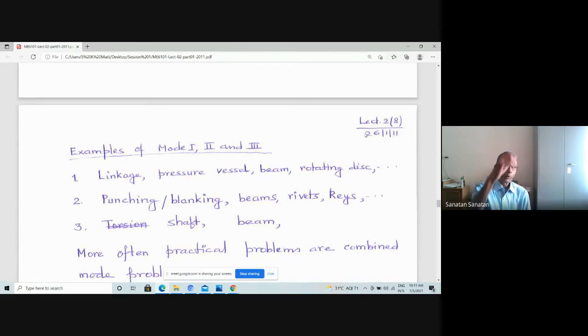Then in the case of a shaft, if you just think of a keyhole, or rather a notch made around the circumference, then when you are twisting it, one side of the shaft and the other side are trying to have displacement in the circumferential direction, and it is really giving rise to mode 3 loading. And therefore, these are actually practical examples.